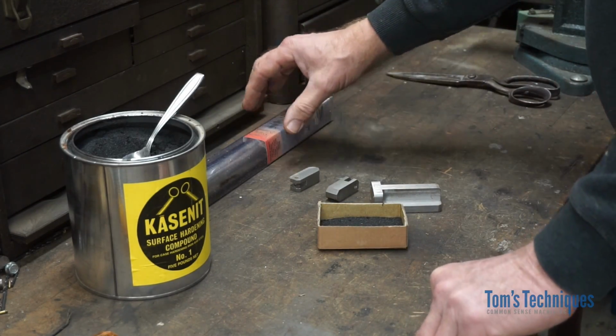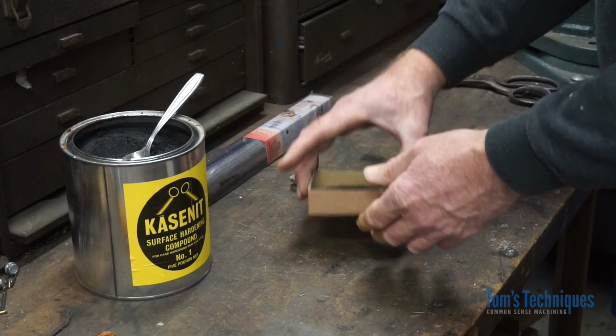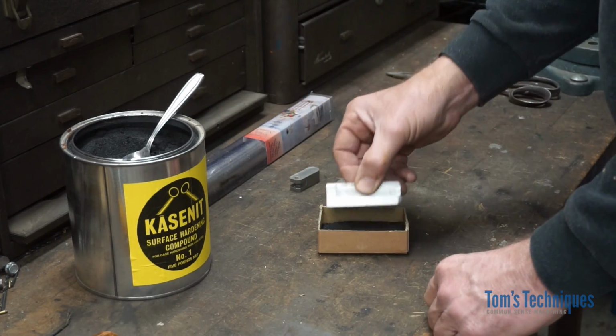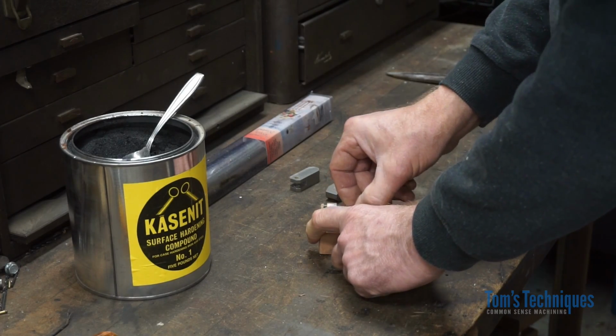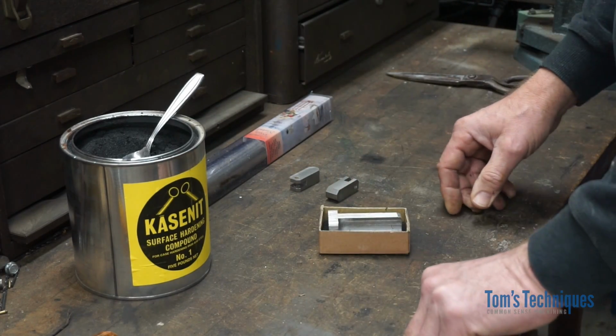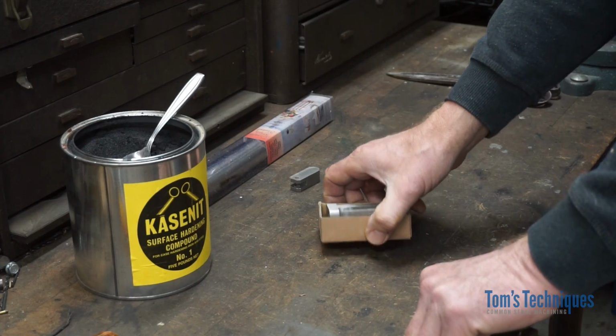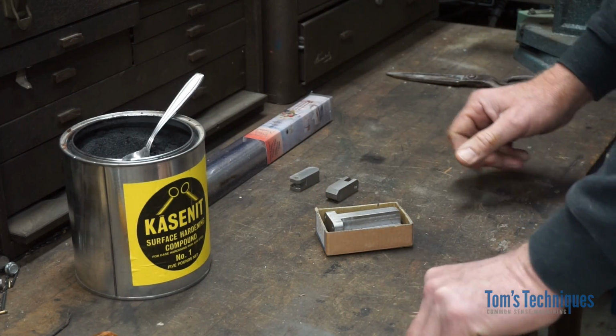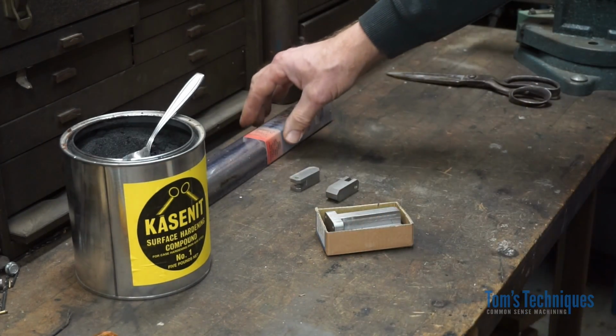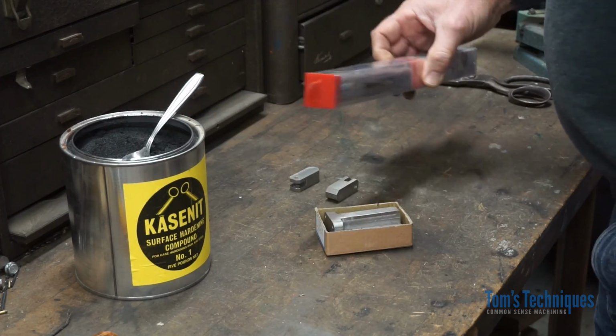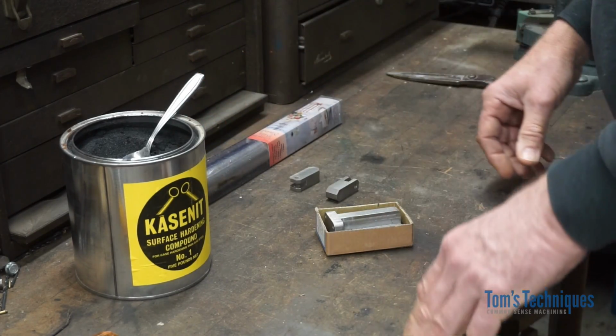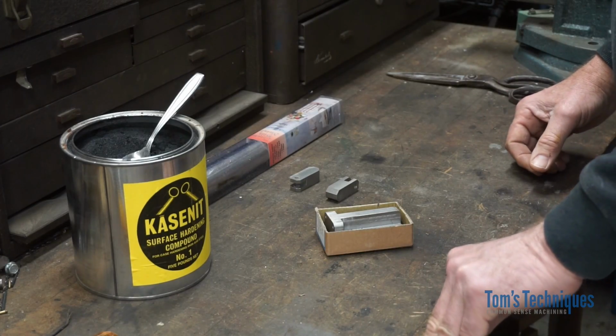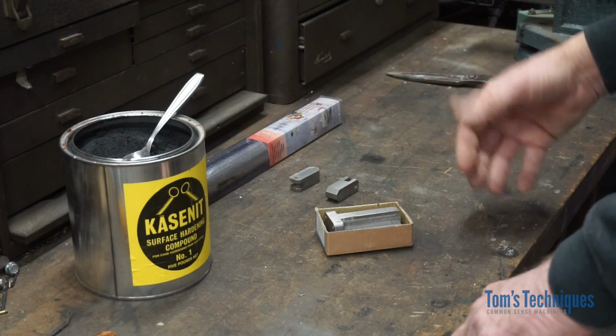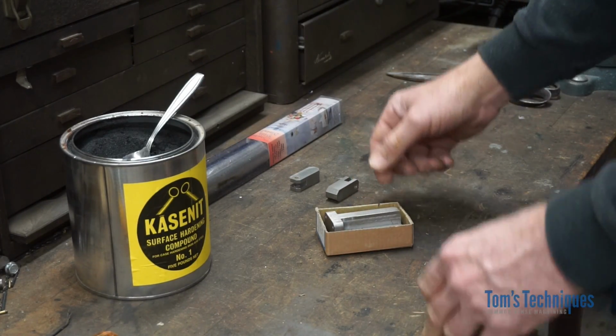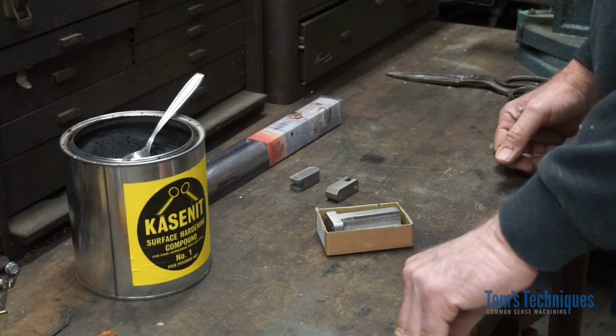So what I do is immerse these things in the powder, and then I either wrap them in paper or, in this case, a cardboard box, and then you put this whole assembly inside a stainless steel envelope and seal it all up. So it's inside a sealed container. And so when you heat it up, the cardboard or paper or whatever burns and consumes whatever oxygen's inside the envelope.